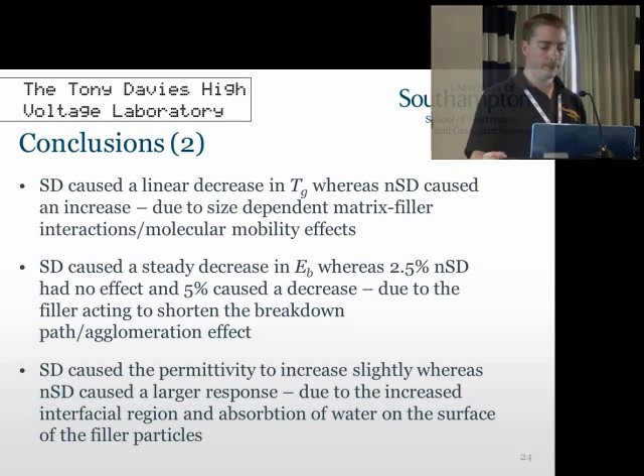When we looked at the permittivity, this obviously gave us a good indication of what was happening and why the breakdown strength was decreasing, simply due to the water absorption on the surface of the particles, which then led to an increase in the permittivity, which related to the surface area of the filler present.